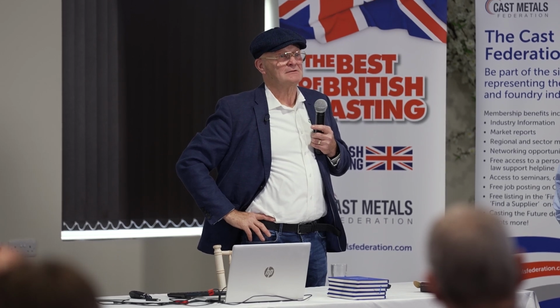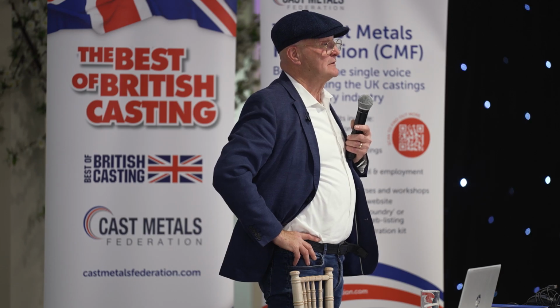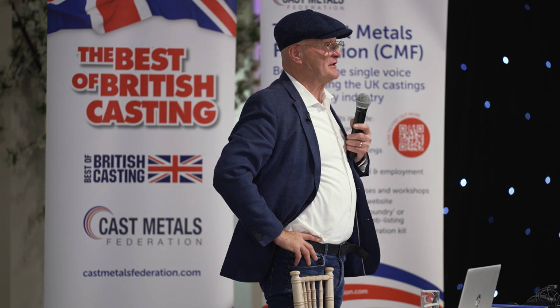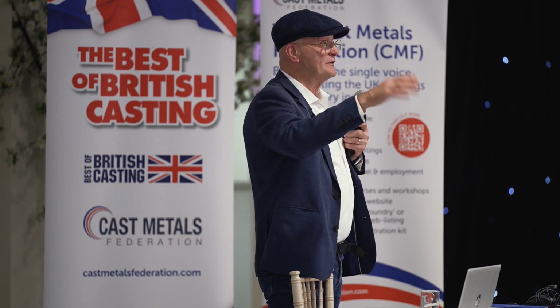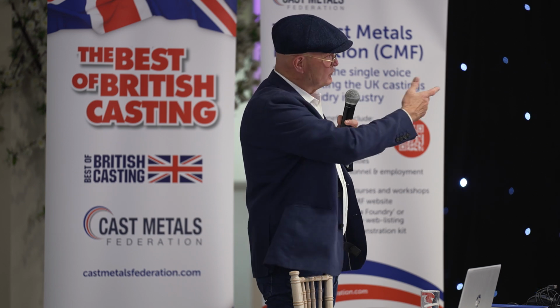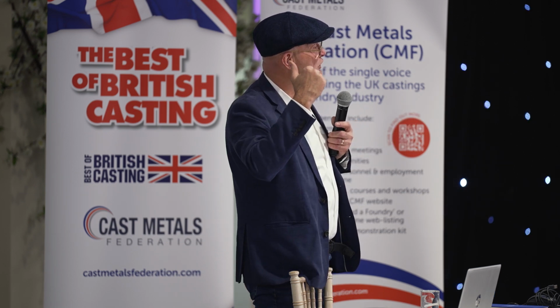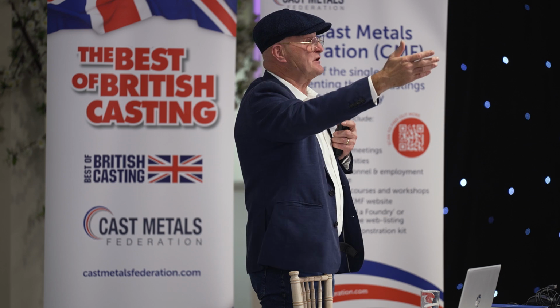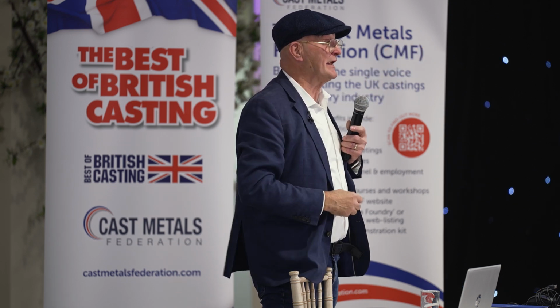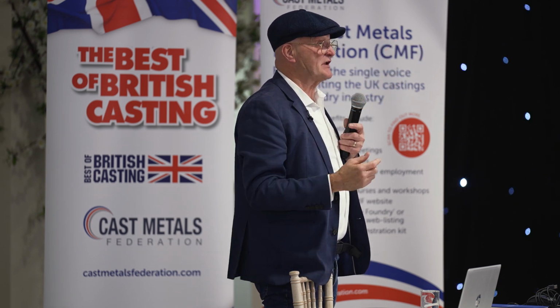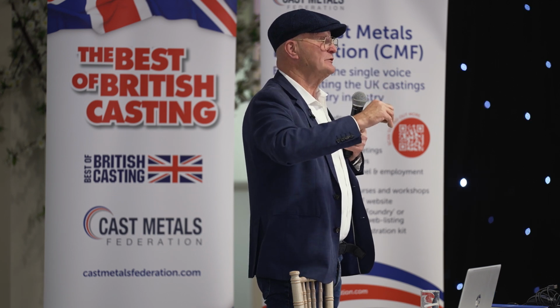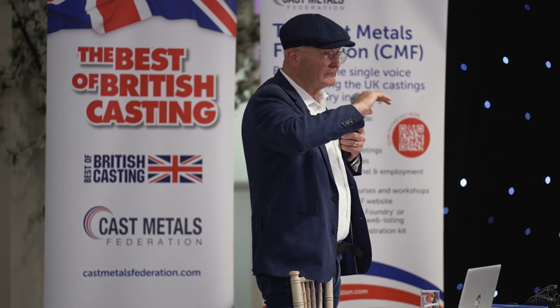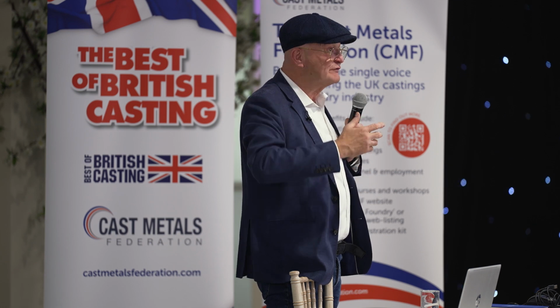So, yeah, because when they were shot blasting the scale material, right? Yeah, the scale, it peens into the surface. Yeah. Scale when you machine it, whereas you Yeah. So because you had less scale, you had less peening. And as I said, the 10% that is there, you can wipe it off with a leather gauntlet when it's cool enough, which is what was found on that ladle heater in your workshop. You just rub it, and it's only 310 stainless. It's nothing magical like Inconel. It's just 310 stainless, but you don't get the impingement that you get from a flame that wrecks virtually everything it gets in contact with over time.